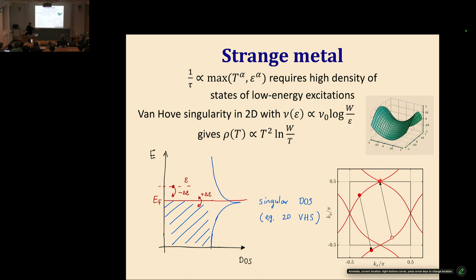This is a saddle point in terms of the dispersion, epsilon versus k. It would look like this. Specifically in two spatial dimensions, it turns out that if you calculate the total density of states, that actually has a logarithmic singularity exactly when the Fermi level is at this saddle point. And that means that there are much more electron-hole pairs available to scatter our quasi-particle if the system is tuned to the vicinity of this point.